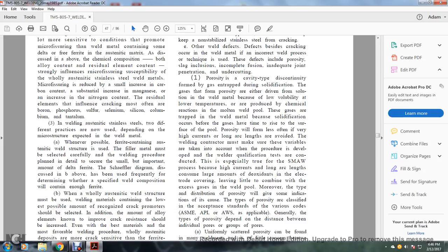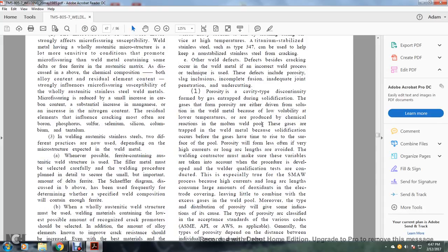1. Porosity is a cavity-type discontinuity formed by gas entrapment during solidification. The gas is either driven from solution in the weld metal, or produced by a chemical reaction in the molten weld pool. The gas is trapped in the weld metal because solidification occurs before the gas has time to arrive at the surface of the pool. Porosity will form less often if very high currents or long arc lengths are avoided.